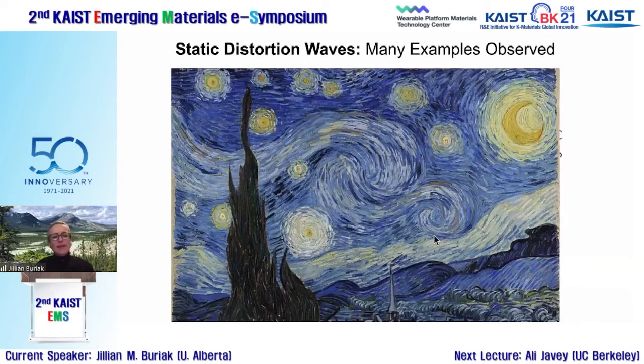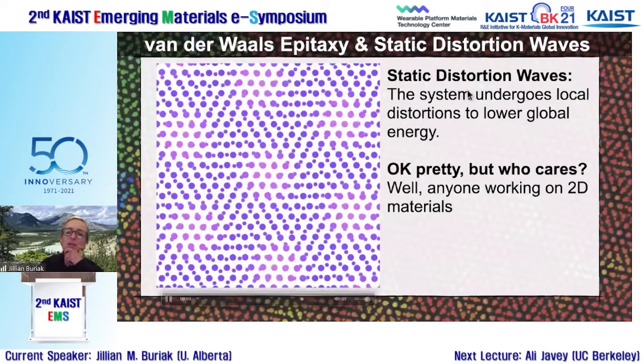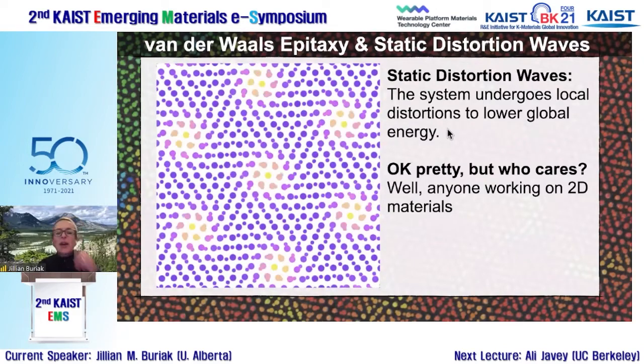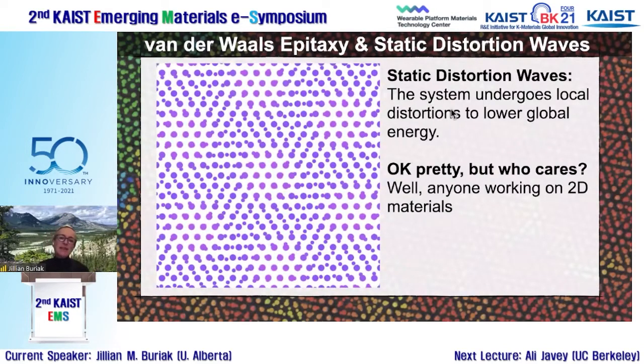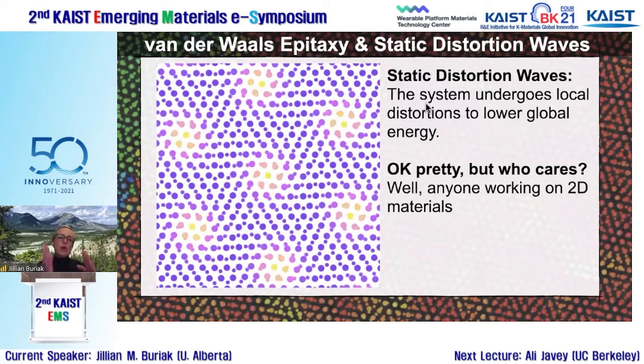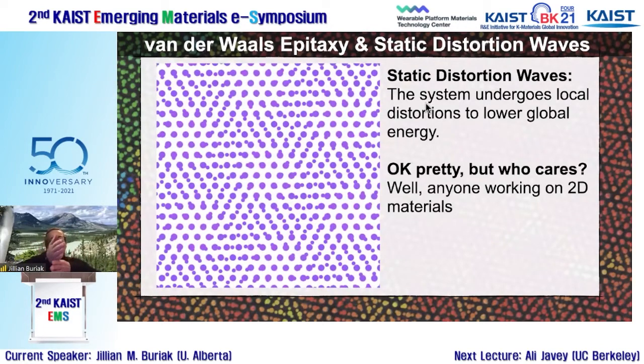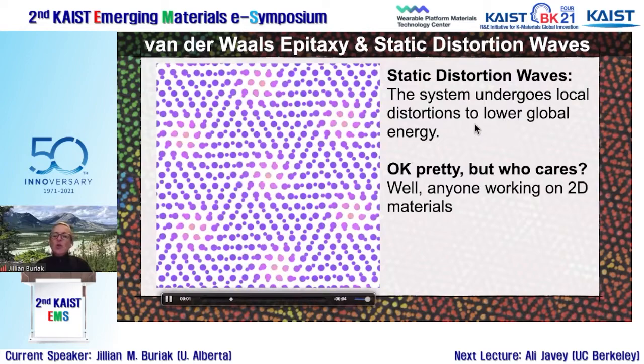So what this led us into is that these are in fact static distortion waves, and/or mass distortion waves, depending on which physics class or who taught you physics when you were an undergrad. What's happening is that in addition to the Moiré superstructures being formed, in which the two lattices adopt an offset in order to reduce the global energy of the system, it undergoes a final little twist in the core, which also adds to lowering the global energy. And so we thought, oh, isn't that kind of cool?